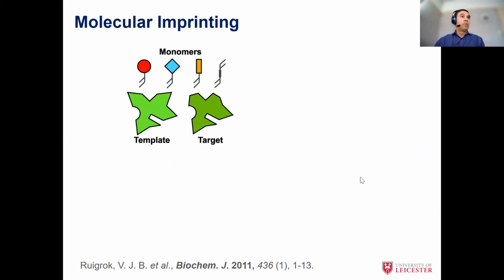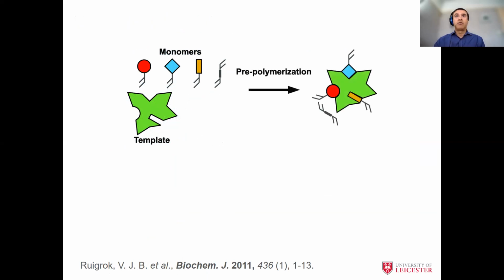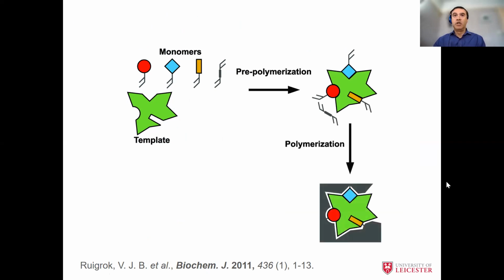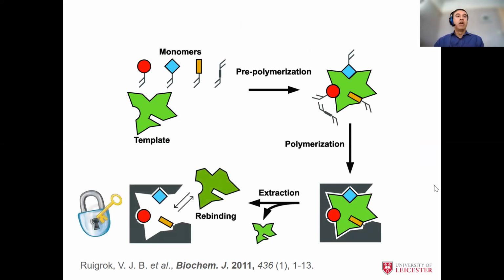So a little bit about the chemistry. Essentially you have functional monomers that have double bonds, they're polymerizable. So we're using polymer chemistry, radical polymerization chemistry. You have your target, which is what we call the template, and a complex forms through non-covalent interactions of the monomers with the template, and you induce polymerization. Once you've induced polymerization, you can then remove the template that is bound non-covalently, so you just need to use very mild acid or base or a solvent that can remove the template, and then you're left with an imprint that is complementary to the shape of the target. That is called molecular recognition, and that is a molecularly imprinted polymer.